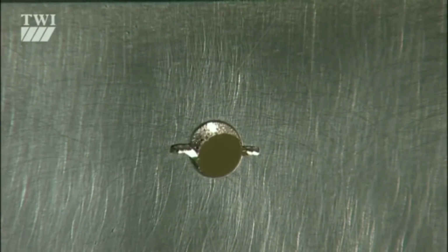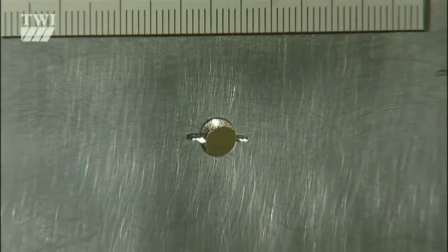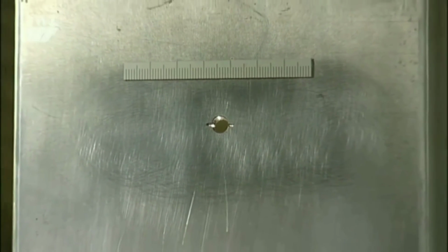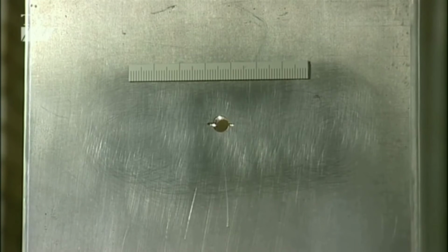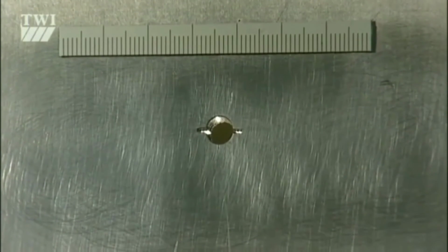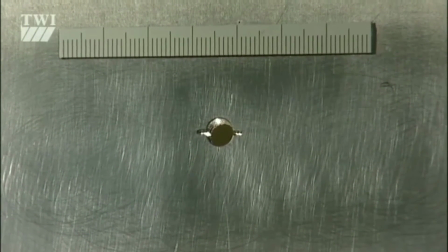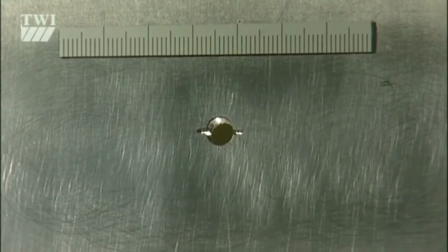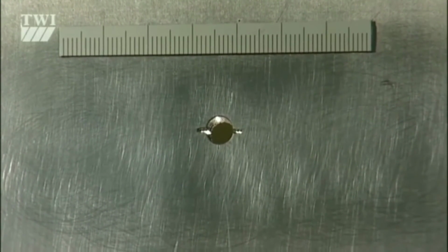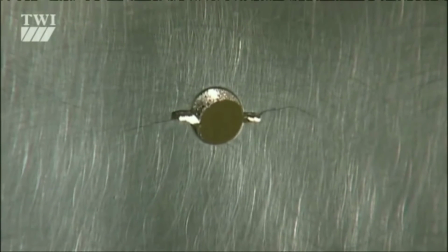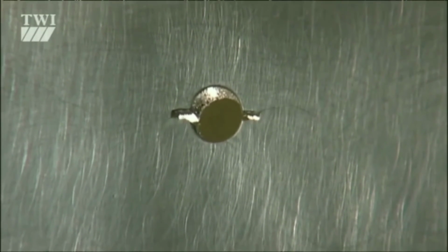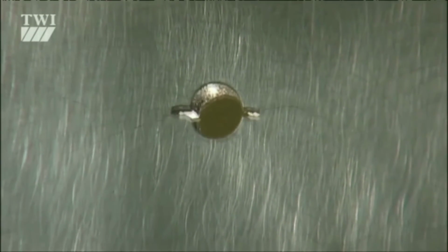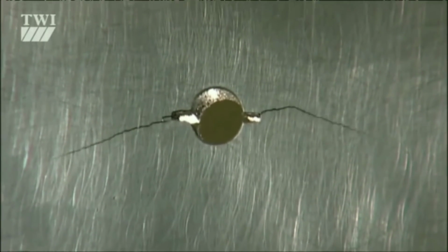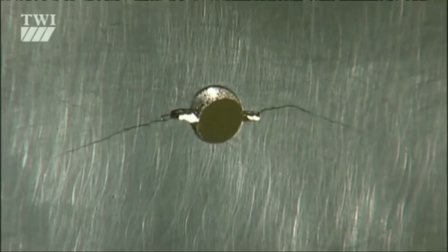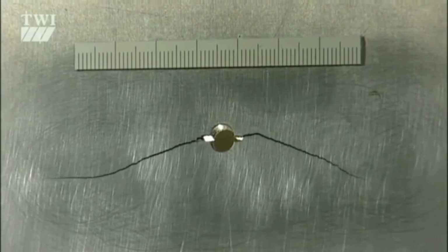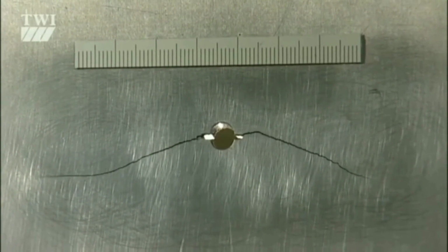We can clearly watch a fatigue crack growing by testing this aluminium plate specimen in a fatigue test machine. By compressing time, we can speed up the view of crack growth. The test piece has an artificial stress concentration so that the crack is located accurately. By polishing the surface, we can see the crack propagate. First 10 millimeters, then 30 millimeters, to final failure.